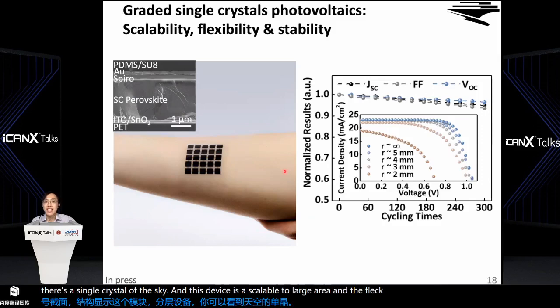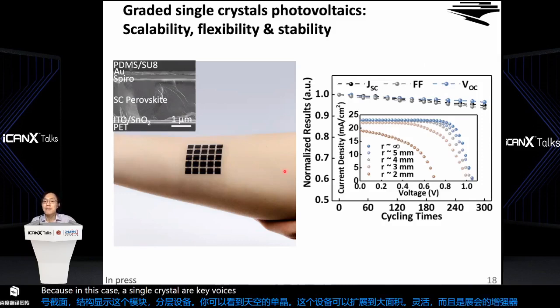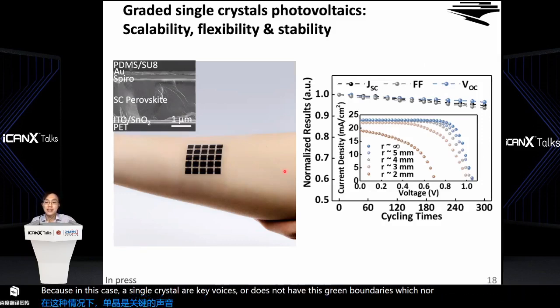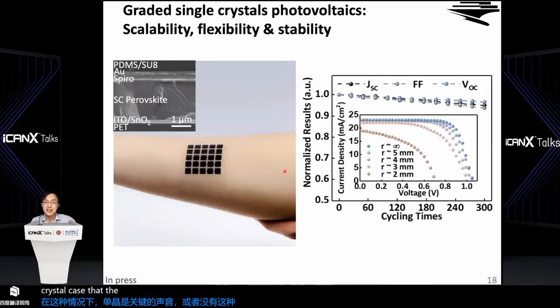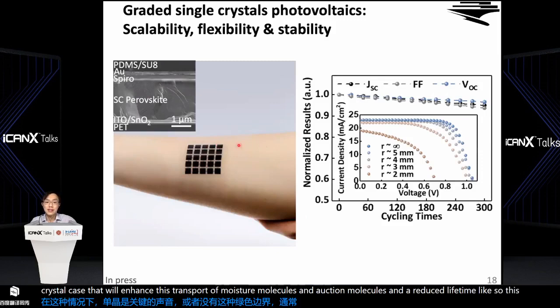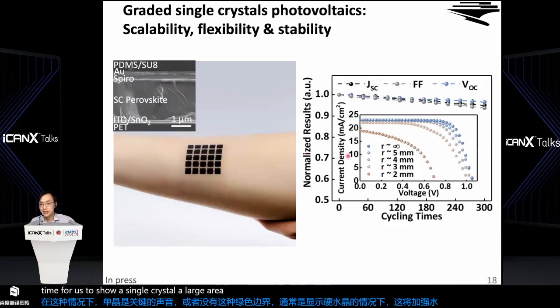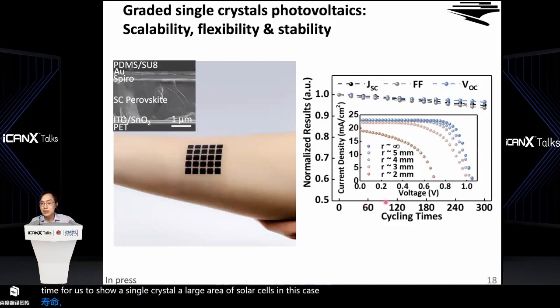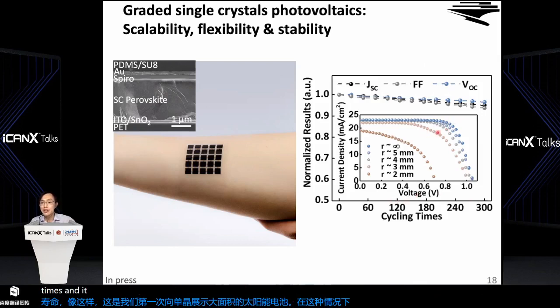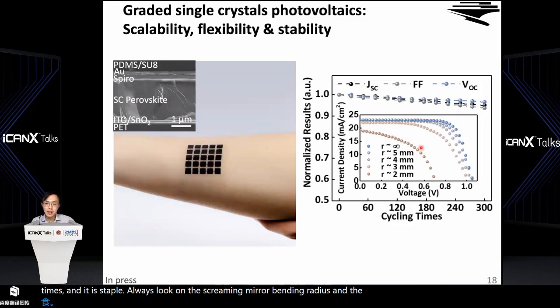And also it shows enhanced stability, because in this case, a single crystal device does not have these grain boundaries, which normally show in this polycrystal case, that will enhance this transport of this moisture molecules and oxygen molecules and reduce lifetime, right? So this is the first time for us to show a single crystal large area solar cell in this case. And this device can be bent and released for cycling over hundreds of times. And it is stable when it is bent to around 3 millimeter in bending radius. And if you keep bending them, then the device will collapse due to this material delamination at the interface.